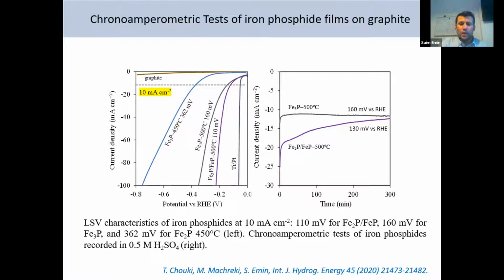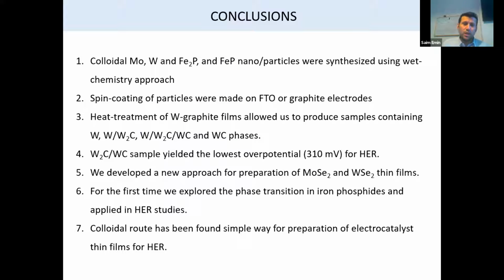And so we were able to produce film very stable, that kind of films. The current is very stable. Here we tested these films at 160 millivolt applied voltage and recorded the current. For one of the samples, you can see it is very stable. The other shows a little drop in activity, which means metal phosphides are also very good for hydrogen evolution studies.